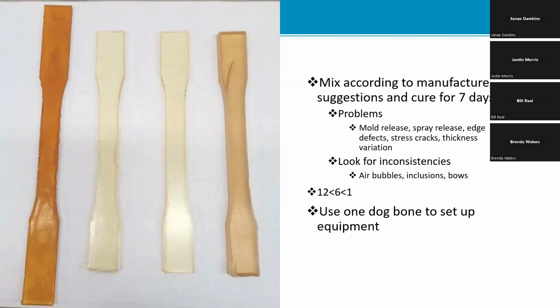So it's very important when you're using these molds to make sure you inspect the mold. And some of the things you want to look for are inconsistencies. If you have air bubbles in the dog bones, that's going to interfere with the tensile strength. If you have inclusions, that's also going to interfere with the tensile strength. If you have any bows, for example, you may have more sample in certain parts in the middle of the dog bone, that's also going to interfere with it. So when you're making these molds, you have to make sure you inspect the molds first. And when you get the dog bones out, you want to also inspect those.